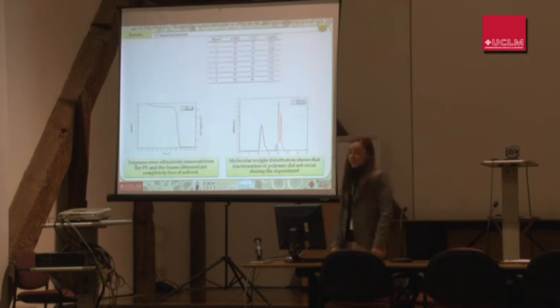Finally, we determine the concentration of the remaining terpene oil that was inside the foams, and we observed that they were practically free of solvent, and also no change in the molecular weight distribution was observed.